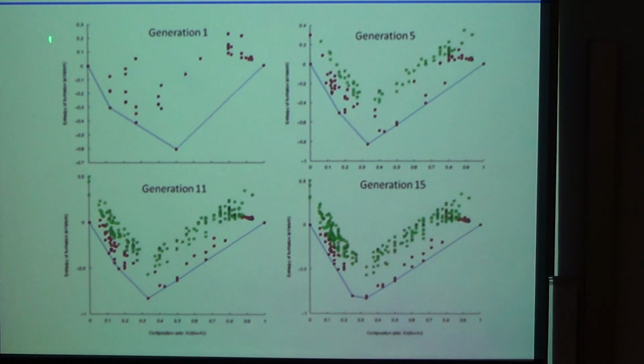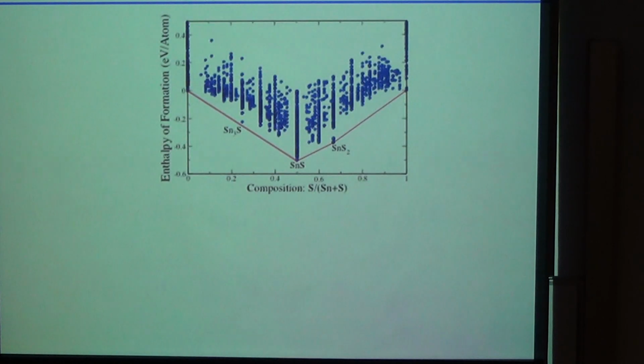So in the first generation, we have some points here. Then we do generation 5. Then we see that new compounds start appearing, generation 11, generation 15. And we run this search for many generations until we see that the convex hull doesn't change for the last, for example, 10 generations. So it means that we completed our search. Theoretically, it's impossible to find all the compounds, but because of the complexity, we just stop.